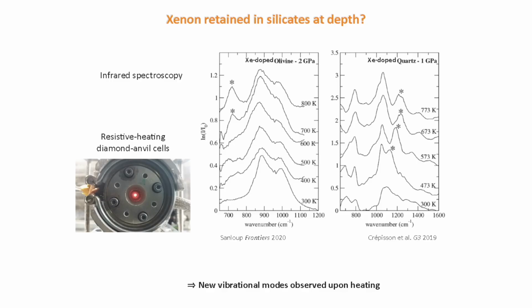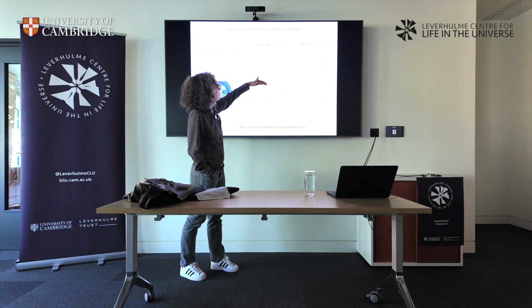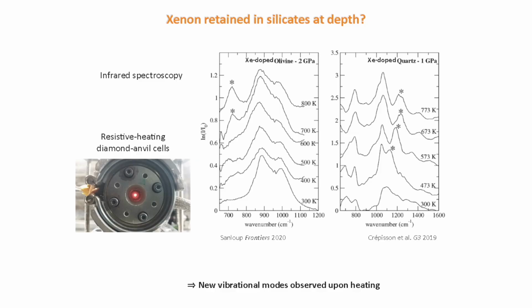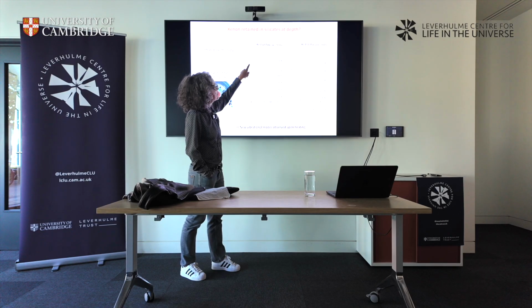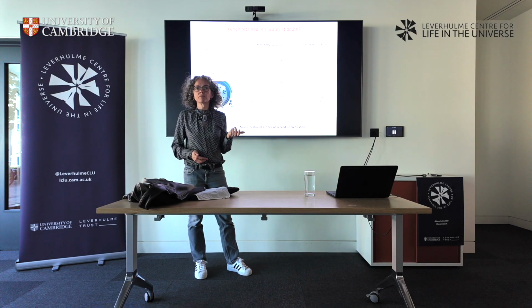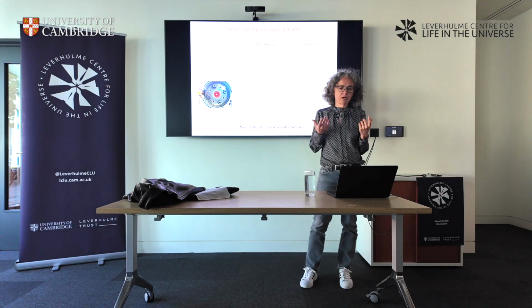On both sides, the sample is compressed, and then we slowly heat. So initially, we have the typical infrared spectrum either of olivine here or of quartz here. And when we heat, we observe new vibrational modes in both cases. And when we decrease the temperature, they vanish. So we observe new vibrational modes. We also have Raman spectroscopy indicating that. So we have some proof of interaction of xenon with the SiO2.